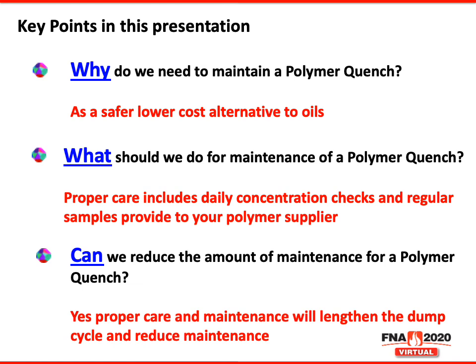What should we do for maintenance of a polymer quench? Well, you need to start with running daily concentration checks and providing regular samples to your supplier. Because remember, CQI-9 states that if the bath or solution is older than 4 months, you need maximum cooling rates and you need cooling curves. Your supplier will also run other tests, such as the viscosity, to make sure that the polymer hasn't sheared. Refractive index, to once again make sure the polymer hasn't sheared. Your supplier will run biological tests if you've been having a history of bacteria and yeast, mold, and fungus. Your supplier will also run the cast iron chip corrosion test.